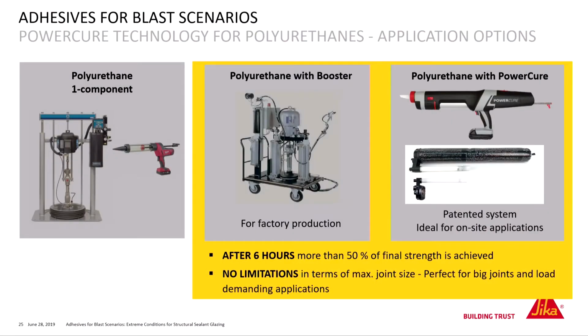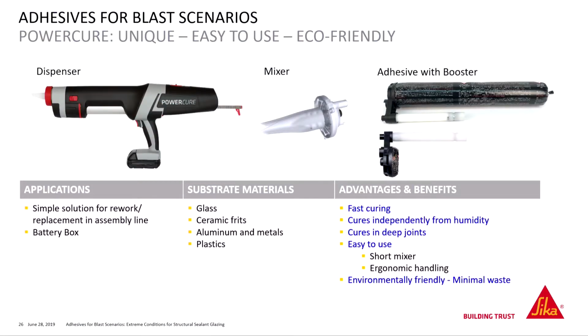It reaches 50% of the final strength after 6 hours. And on top of that, we have a nice behavior here. There is no limitation, or I would say almost no limitation, of the maximum joint size, joint bite. When you consider one-part silicone or one-part polyurethane, maximum joint bite is limited to 15 millimeter, 18 millimeter maximum. And here we can go to 20, 30, 40 millimeter, as long as you can apply it properly. Okay, then let's look at these details a little bit more.